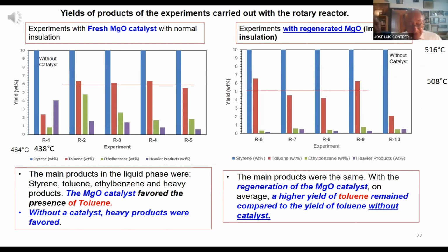Here, in the experiments with fresh magnesium oxide catalyst with normal insulation, the catalyst favored the presence of toluene, similar to the experiments with regenerated catalyst and improved insulation. Toluene production, on the other hand, was lower in the experiments without catalyst.